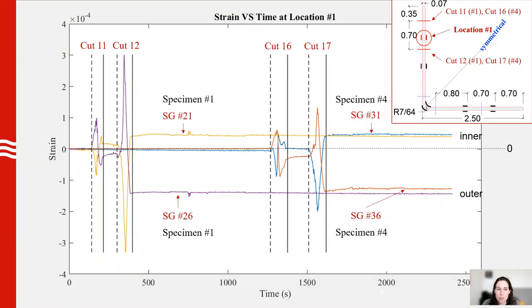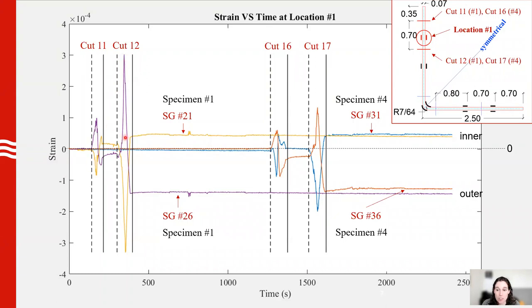Here's an example of what our strain versus time looks like at location one, done for both our edge and center piece. For specimen one, that refers to cuts 11 and 12 — on both sides of location one — and strain gauges 21 and 26 for specimen one, and 31 and 36 for specimen four. This shows the released strain after sectioning. The dashed line is where we start the cut and this is where we finish. You can see there's a lot of movement — readings change significantly when making adjacent cuts, so we need to wait for it to stabilize. After the cut, it does stabilize and reaches a plateau. Same for cuts 16 and 17.